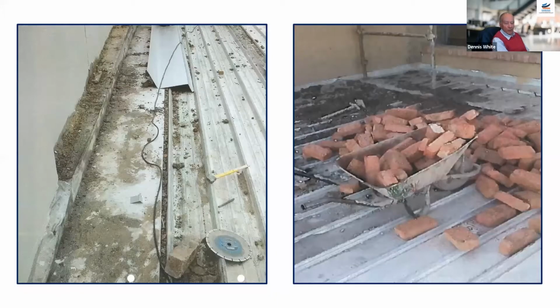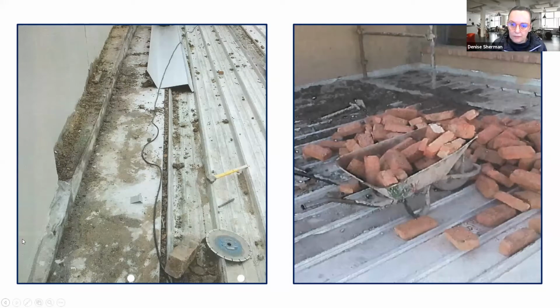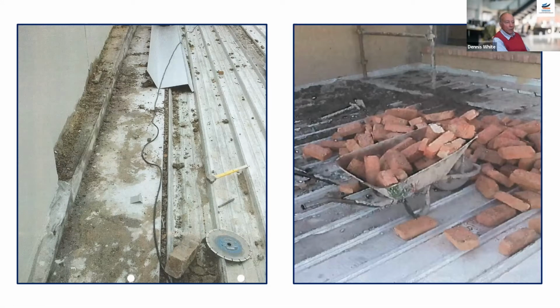No, go ahead. Okay. Yeah, what I just wanted to ask was about what do you do with wet bundles or packs of material? You've got to separate those laminal or layers or sheets, whichever reference you want to make, and dry them off. You've got to get rid of the moisture as quickly as you possibly can. And unfortunately, on a site, you don't have the luxury of vast areas where you can take the sheets and lay them out in the sun to dry out. So these things have got to be dried off. And then we recommend, when those bundles are reconstituted, that there's something separating each and every sheet until such time as it's installed on a roof.